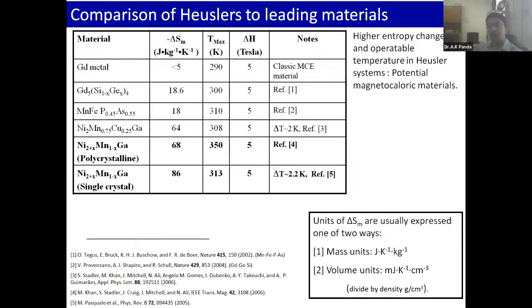So you would certainly look for alternatives, and some of the alternatives are subsequent ones. We go for nickel, manganese, copper, gallium, basically a modification of nickel, manganese, gallium, and there are 2 effects basically. One thing is nickel, manganese, gallium shows a peak. This is polycrystalline, and you have 68 joules per kg Kelvin, which you can raise by making it a single crystal, with an entropy of 86, because that is much more facilitated in terms of magnetization as well as the phase transformation.